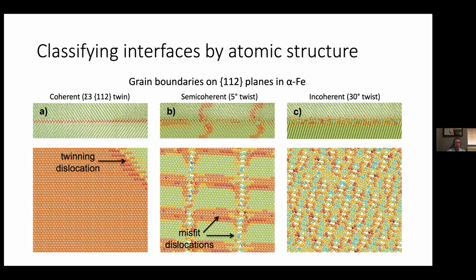Over here on the bottom, I'm showing you a view of just the atoms that are right at the grain boundary plane. So if I were to just cut out the atoms right here at the plane and flip them over by 90 degrees so that rather than looking edge on, I'm looking into the plane of the boundary, this is what the plane of the boundary looks like. And what you can see is that it's very well ordered, right? So the atoms are basically matching on both sides. There really isn't much in the way of straining or under or over coordination of the atoms. They're all fairly happy sitting at this coherent sigma-3 twin boundary.